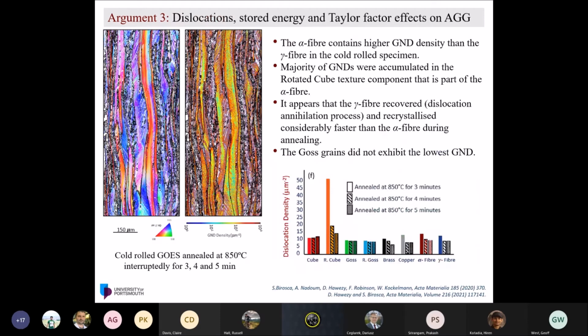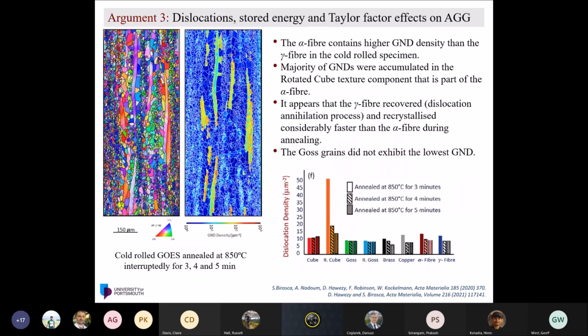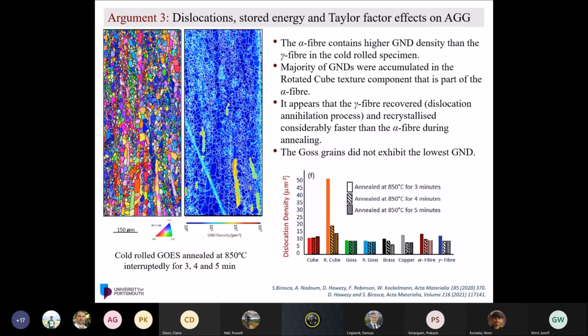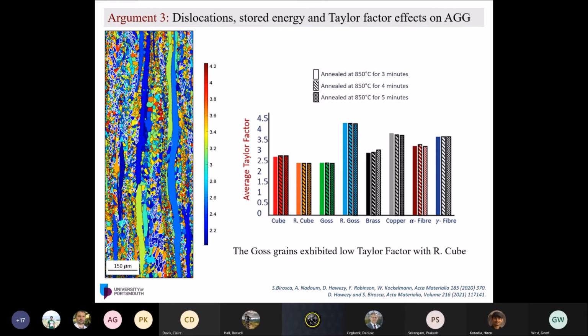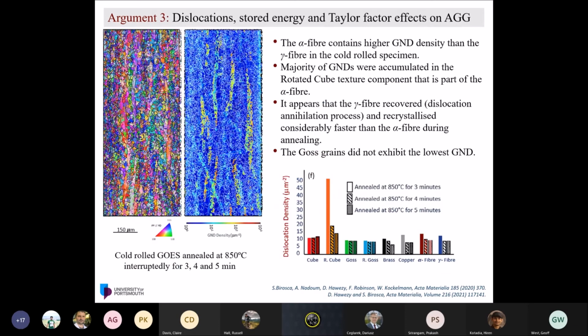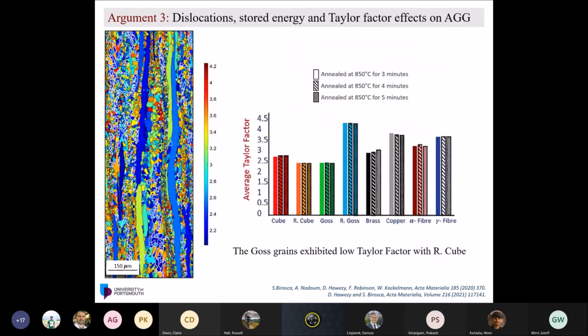Then we tried to understand the dislocation, stored energy, and Taylor factor. And I think this is more related to the recrystallization process during the primary annealing rather than abnormal grain growth. And if you just click a few times, you will see the cold roll. We annealed it at 850 for 3 minutes, and then 4 minutes, and 5 minutes. And this is showing that we were trying to capture the very early stage of the recrystallization, and we looked at it in this way. And okay, that slide is over now.